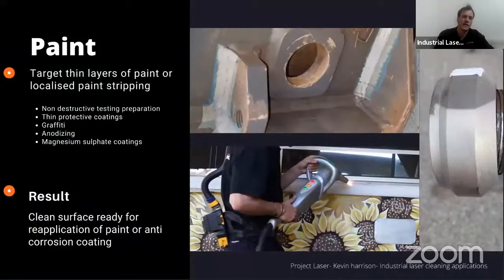It's best to target thin layers of paint or localized paint stripping. On the middle top, that's NDT surface prep, where you're basically just cleaning a 30 to 160 mil band over welds so they can do an inspection. Thin protective coatings, graffiti, anodizing, magnesium sulfate coatings, they all come up really easily with lasers. As a result, you end up with a clean surface ready for a reapplication of paint or an anti-corrosion coating. We can go to the next one.